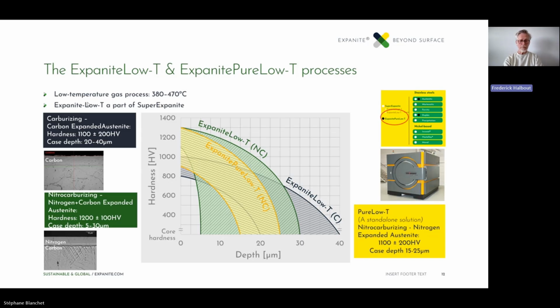In this step, this is where we add the high hardness on the surface. As a standard, the hardness lies around 1,200 Vickers, and the case depth is around 20 microns. There is a new development on this side as well, called the ExpanitePureLow-T process, which is a totally different story, but this is also a process that's done as a standalone for austenitic stainless steels. A little bit more complicated, but the outcome is basically the same. Not all components are suitable for this ExpanitePureLow-T process, but it's been very successful for housings and also for fasteners and bolts and nuts and so on. But that's another story.